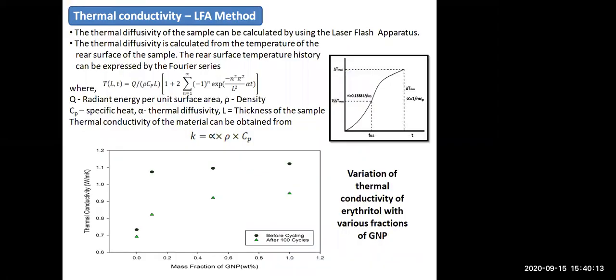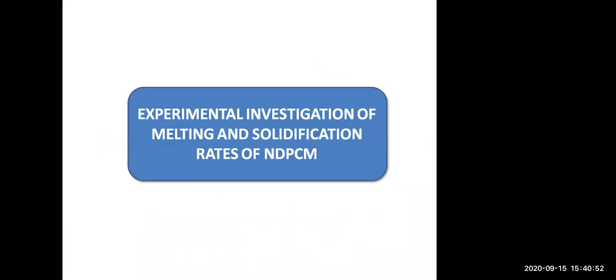Then thermal conductivity by the LFA method. The thermal conductivity of the PCM or NDPCM can be calculated by the LFA method. The thermal conductivity of the erythritol increased with the increase in the weight fraction of graphene due to its high thermal conductivity. The graph shows that the thermal conductivity of the erythritol is 0.733 watt per meter Kelvin. Then the addition of 1% graphene to the erythritol led to a 53.1% increase in the thermal conductivity. That's why we are choosing that.